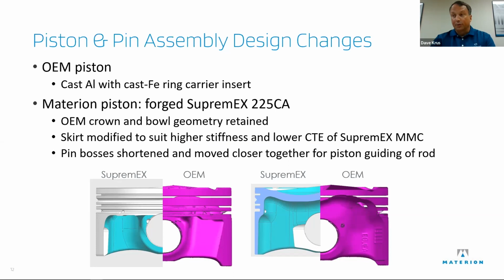So the skirt could be shorter and thinner than the OE. The pin bosses were shortened and actually made it into a piston guided rod rather than crank guided rod. Supremex runs very well on itself. And actually I've got the two pieces here, but you can see that they meet very tightly on the top end, and it ran. These are the ones from the testing, not too much wear on either of those.